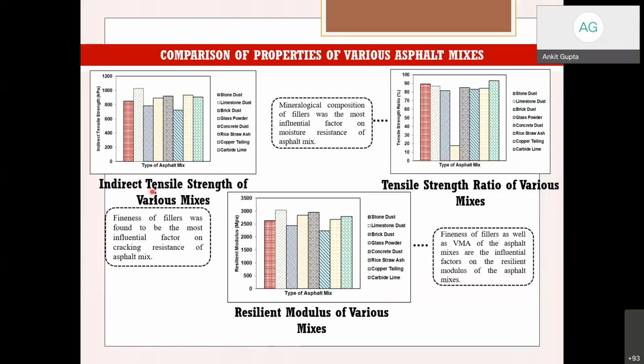Now, with respect to the indirect tensile strength, that is for the fatigue resistance, again the values of the stone dust and the rest of the waste modified mixes are in comparable ranges, and only the rice straw ash has a lower value. Now we have tried to find out the reasons why this is happening. There are some primary reasons: the fineness of the fillers was found to be the most influential factor